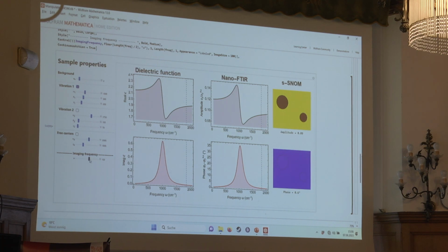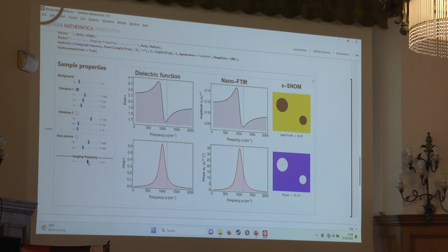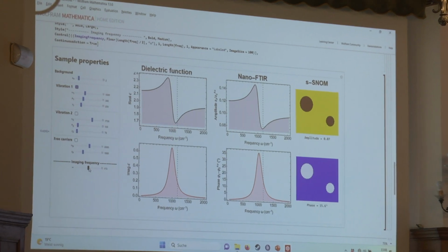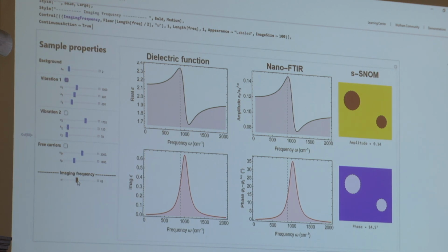And maybe if I hit the peak just right, now the upper image here is really, really dark, because we're here in the minimum, and also of the dielectric function, we're in the minimum. And if we go a little bit to the left, I don't know if the beamer has shown this, but this is now a little bit brighter. And also the number is a bit bigger. But that's probably the reason why we don't look at the s-SNOM amplitude images, because it's really hard to tell what's going on. Whereas here in this phase image, it's a very clear contrast. So it's much easier to interpret.